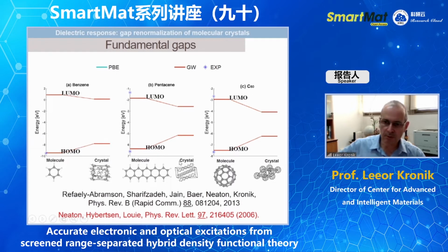As I try to pull out an electron from one of these molecules, all the surrounding molecules polarize in response to the charge that I have there now, and then basically create an image charge. That decreases the ionization potential, increases the electron affinity because it's of opposite sign, and in the end closes the gap. And you can see that it's a very large effect.